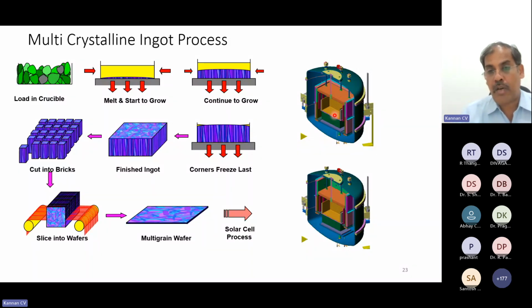There is another technique, by using the same equipment, you can put some seeds at the bottom to try to grow a monocrystalline kind of nature. But once again, the cost is increasing, and the quality is not up to the mark of pure monocrystalline. So even with mono-like multi, the purity of the wafer is not equal to the conventional CZ process, the Czochralski process, where you can grow very high quality monocrystalline wafer. That's why the DSS technique is getting phased out from the industry.